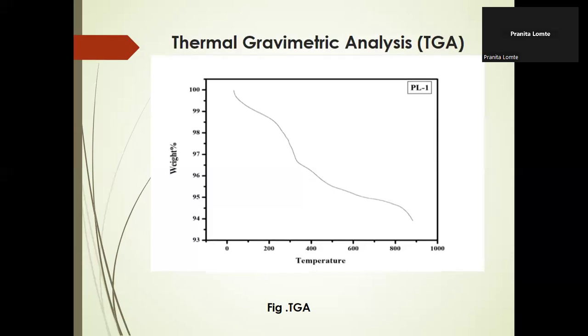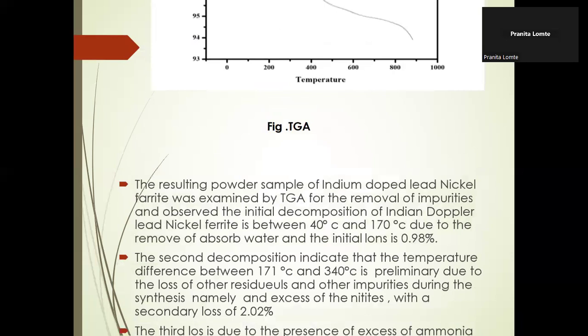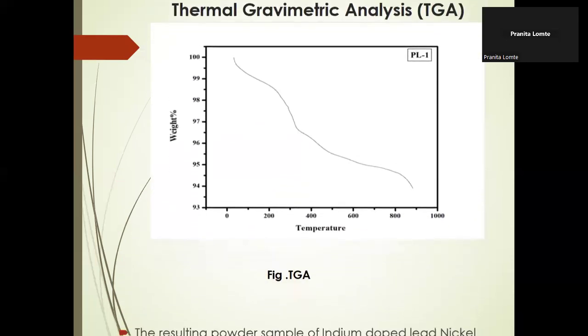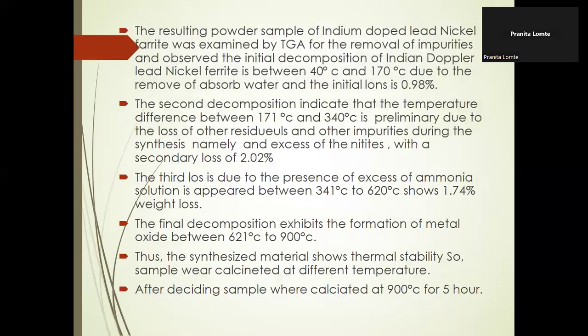So after the conclusion of this graph, we take the result. The resulting powder sample of indium doped lead nickel ferrite was examined by TGA for the removal of impurities. The initial decomposition is observed between 40 degrees Celsius and 170 degrees Celsius, due to the removal of absorbed water, and the initial loss is 0.98%.